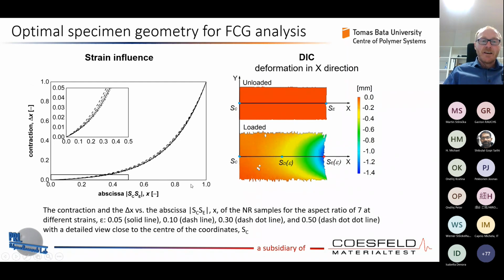We have on the x-axis, that is the abscissa, and on the y-axis a constant contraction. If we have a contraction from this point up to this point, how big is the contraction? That means the deformation. And you can see from the zero point, from the SC, there is always a deformation in this direction. Of course, the largest deformation is at the SA here. That's expectable. However, what is not expectable is that there is always a deformation over the complete width of the sample, independent of the strain. Even if you apply a very low strain, you immediately have deformation there.